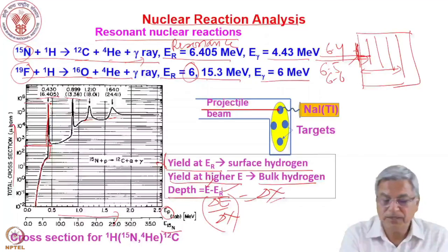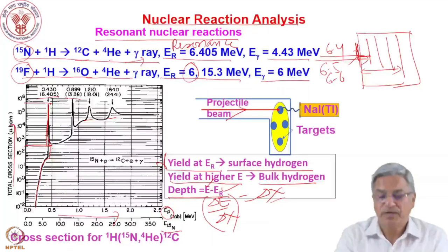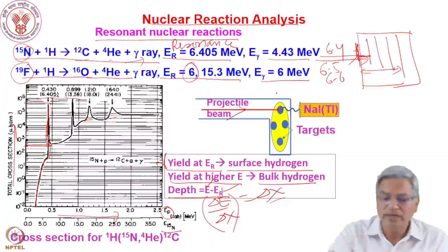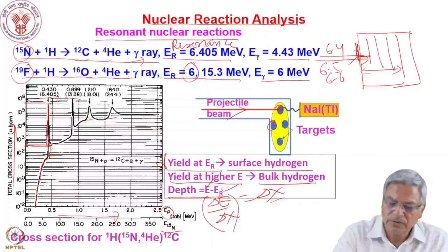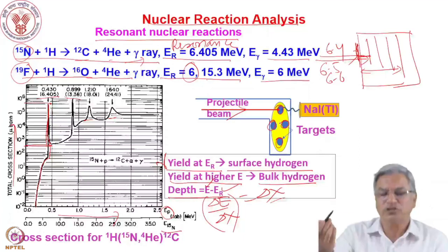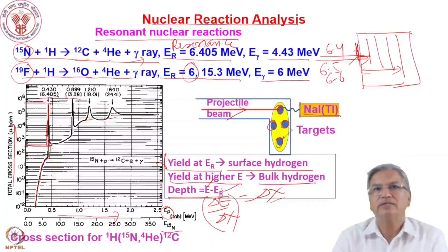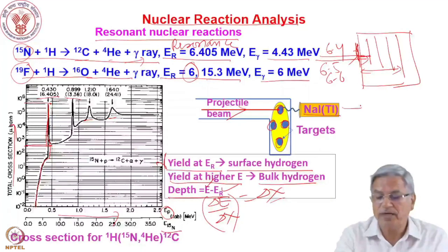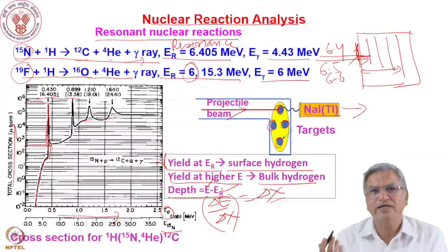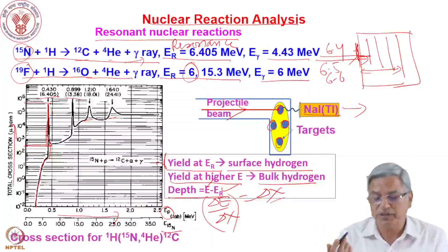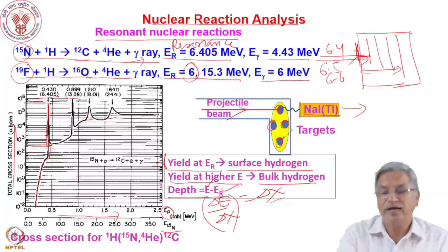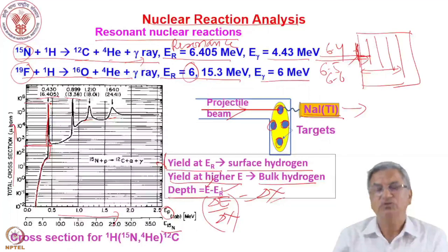You can have a circular rotating target holder with four to six targets; one target comes into the beam path at a time. The gamma energy is known, and intensity is measured with a sodium iodide thallium detector. You do not need a high-resolution HPGe detector since you are not interested in energy measurement. You can measure gamma-ray intensity from multiple targets using NaI(Tl).